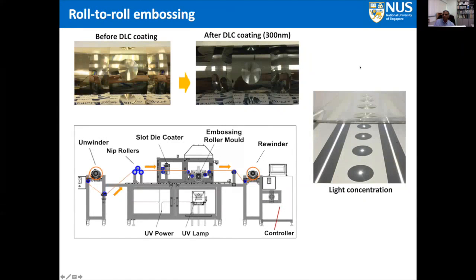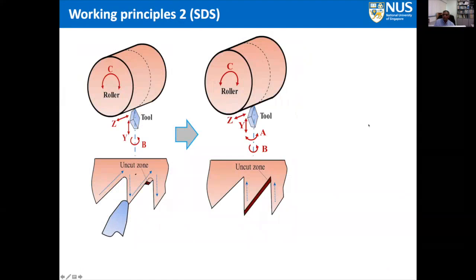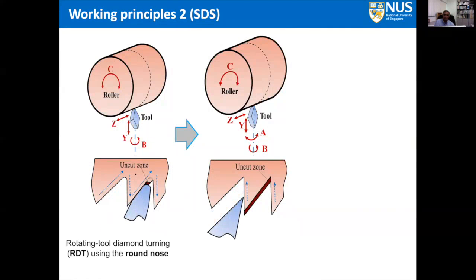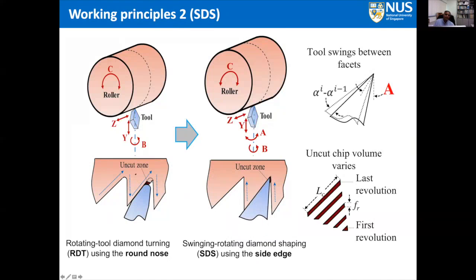This is the lens which is on the top. When the light passes through, you actually see two white lines and then the dots at the center. So in this particular instance, there are situations where the rotating tool has a round nose, and it ends up creating unmachined zones. This is because of the contact of the tool and the workpiece. So what we try to do is create a swinging, rotating diamond shaping technique where this edge is adjusted so that we can produce very deep features. And this tool swings a very small angle, as shown here, so that you can achieve greater depth, up to the point where we need to create a very sharp corner.